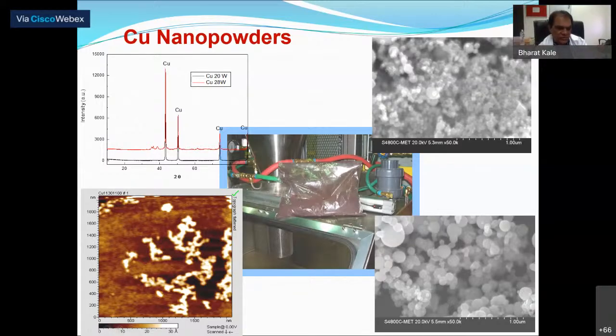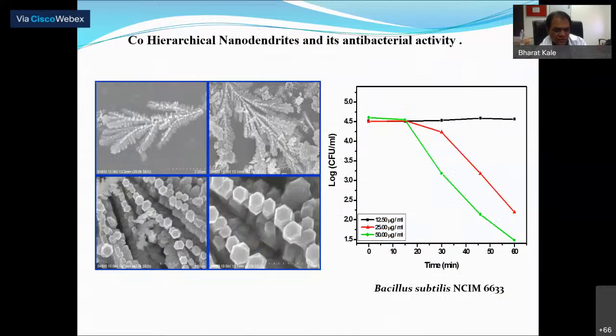This is the bag. You can see this copper nanoparticle. When the size of the nanoparticle is so small, when you open this bag, it automatically gets oxidized. This is an exothermic reaction. The temperature goes to 800 degrees centigrade. It becomes red hot when we open it. Now this is sealed in plastic. You can see the exothermicity of the oxidation of copper to copper oxide, which indicates that the copper nanoparticles have been formed.